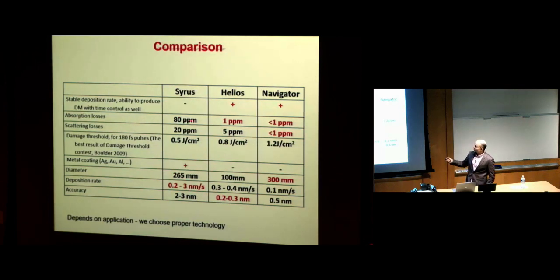A disadvantage of this machine, of course, is that the coating has quite large losses. It's not environmentally stable. It means the properties of the coating in the chamber, in vacuum, are different from the properties when you remove the mirrors from the chamber. The accuracy of the layer deposition is also not the greatest. If you consider magnetron sputtering, it cannot deposit as large optics as an electron beam machine, but it can do very low absorption coating. Unfortunately, the scattering losses are slightly higher than the absorption losses. It has a relatively fast rate.